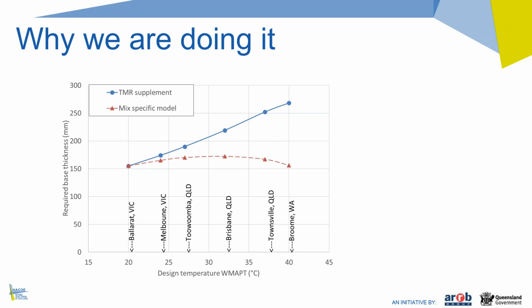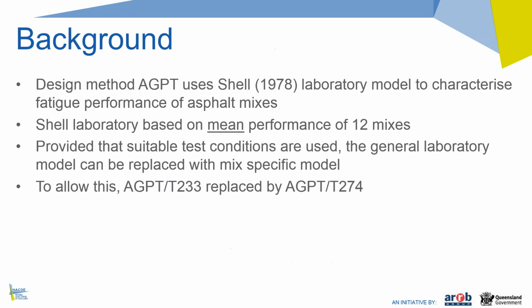If, however, you use a mix-specific model, and this is a mix-specific modulus and a mix-specific fatigue model, that's not necessarily the case, because the fatigue model especially is more temperature sensitive. And as you can see here, for one of the mixes that we tested under the TMR research program, if we do the design based on using those models, we actually do not end up with a thicker pavement in Brisbane than in Melbourne, which would make us very happy. And the Queensland taxpayer as well.